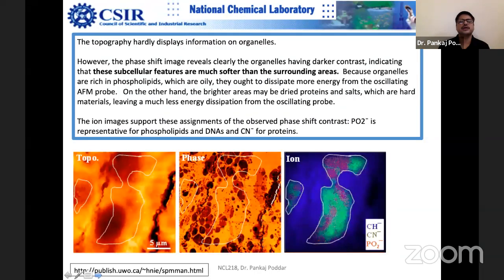some other image. This is a cell image, and you can see even subcellular information. This example is quite nice, because normally the complaint is that AFM doesn't give you subsurface information. But here, because it is slightly tapping, you get the subsurface information also, which is not possible in the non-contact mode. Non-contact mode tip is not touching the surface, so you do not get the elastic properties of the surface.